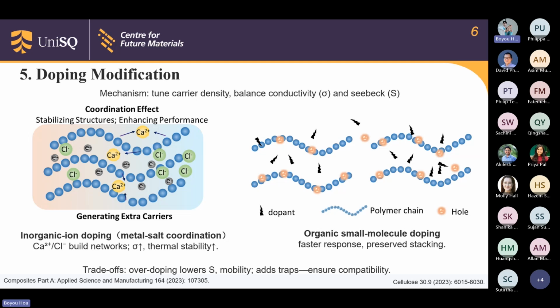The other approach is organic small molecule doping. Here, small acid molecules dope the conducting polymer, tuning carrier density while preserving chain stacking. Both routes use doping to set carriers and stability at the same time. Metal ions give coordinated networks. Small molecules give quick response and strong voltage, provided we avoid overdoping and ensure good compatibility.